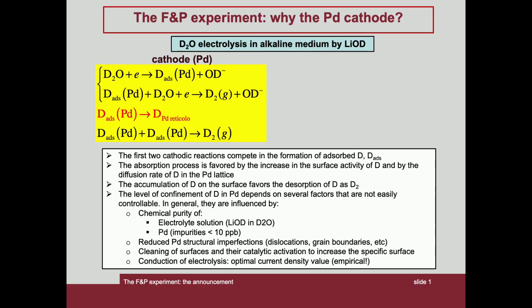In general, they are influenced by the chemical purity of the electrolyte solution and the impurities present in the palladium that should be less than 10 parts per billion. Further, the reduced palladium structural imperfections, cleaning of surfaces and their catalytic activation to increase the specific surface area, and conduction of electrolysis by choosing the optimal current density is just an empirical way.